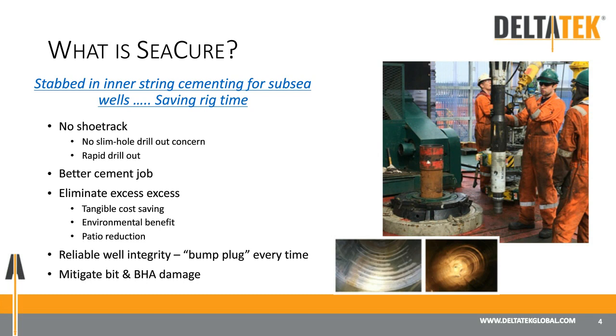And there was no difference in the drilling parameters to the drill out of this cement than there was to any other shoe track. However, quite surprisingly, when that casing was pulled across the area where the cement was seen and the cement was drilled out, there was substantial quantities of the casing missing. In actual fact, the operator measured the amount of casing missing, and 66% of the steel casing was no longer on the casing and would be normally in shoe track drilling processes somewhere in the wellbore.